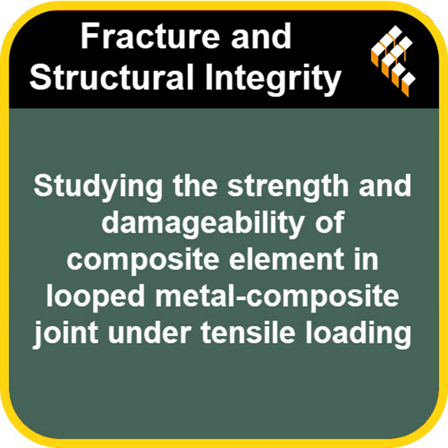Definitely. So, to recap the key findings. This study showed a really effective engineering technique for designing these metal composite joints, their composite loop. It absolutely had the required tensile strength. Check. The experiments matched up well with those complex nonlinear calculations. Double check. And crucially, the acoustic microscopy confirmed the carbon fiber structure itself wasn't fundamentally damaged, even when loaded 20% beyond its design maximum. Which is impressive resilience.